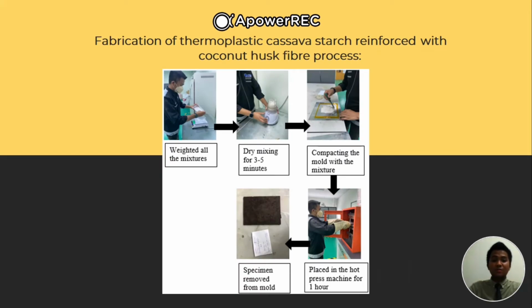Fabrication of thermoplastic cassava starch reinforced with coconut husk fiber process. First, weigh all the mixture. Second, dry mixing for 3 to 5 minutes. Third, compacting all the mixture into the mold. Next, place into the hot press machine for 1 hour. Lastly, the specimen is removed from the mold.